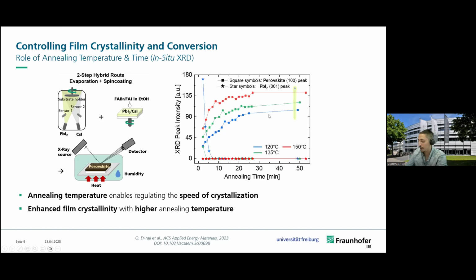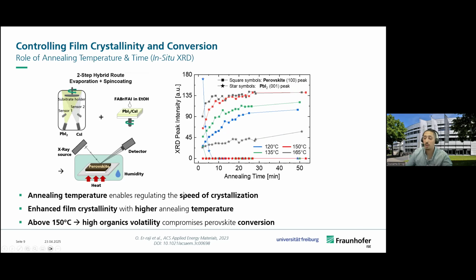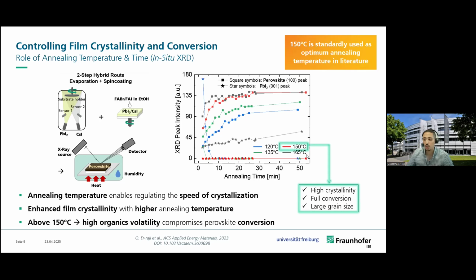Now, what happens if we go to an even higher temperature, 165 degrees? We see a similar pattern with the perovskite, but here the lead iodide peak does not go to zero, which shows us that above a certain temperature, the organics become highly volatile. They do not diffuse within our inorganic scaffold, and therefore this raises the issue of full conversion. So it's very important to optimize the temperature, and from this experiment we can see that 150 degrees is really an optimum between high crystallinity and large grain size, but also full conversion. And this might also explain why in the literature you will usually see that people use 150 degrees as an annealing temperature.